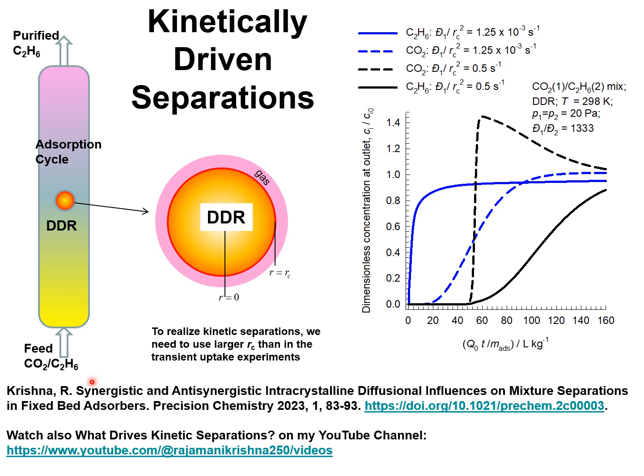I consider transient breakthroughs in an adsorber packed with a DDR zeolite. The feed mixture consists of an equimolar mixture of CO2 and C2H6 with partial pressures 20 pascals each, and the breakthrough simulations have been carried out for two sets of conditions.